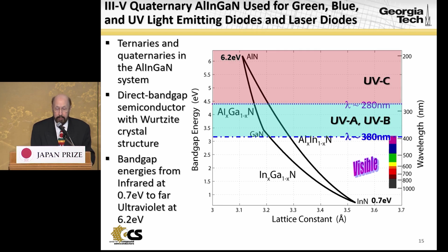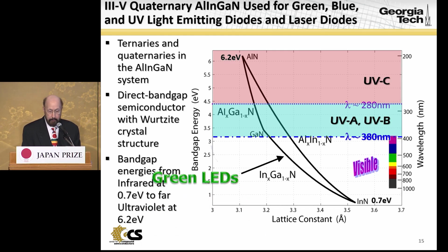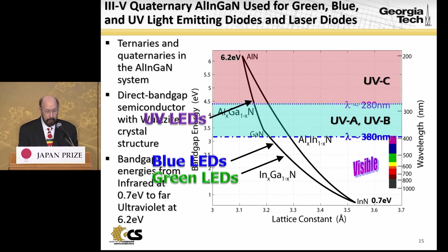The other quaternary of very extreme interest is the aluminum indium gallium nitride quaternary, shown here again in band gap energy versus lattice constant for these wurtzite crystals. These are all direct band gap alloys and binaries, with the endpoints being about 0.7 eV for indium nitride and then the ultraviolet 6.2 eV for aluminum nitride. So this quaternary can easily cover the important spectral regions of green, blue, and ultraviolet LEDs and laser diodes, and is being actively researched today throughout the world.